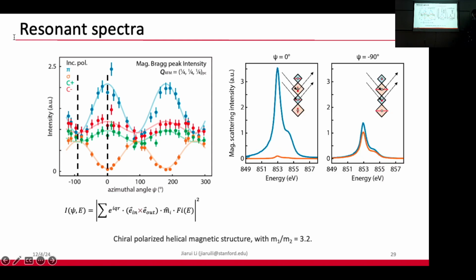And there is further information that we can extract from this kind of measurement, as we see that there exist two high symmetry positions. For example, azimuthal angle at 0 and at plus or minus 90, like 0 and 180 or minus 90, where the magnetic Bragg peak intensity is maximized or minimized in the two different channels. And this corresponds to the magnetic moments being in and outside of the scattering plane. And this is very interesting, that by selecting the polarizations at these two special angles, we can selectively enhance or reduce the photon and spin interactions on half of the spin sites.